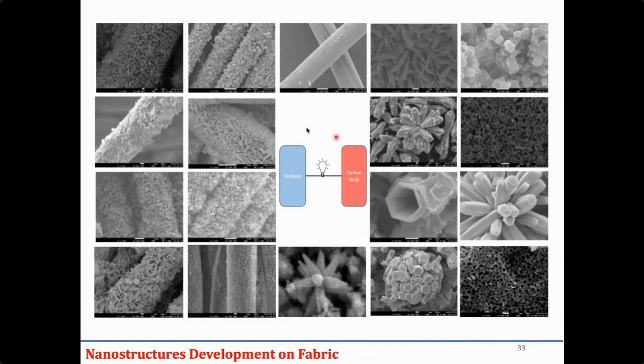So that is the way we try with the different nanostructures, and even porous structures. When we make porous structures, more scattering will occur. Due to that more scattering, it can decrease the phonon transport and it increases the efficiency.